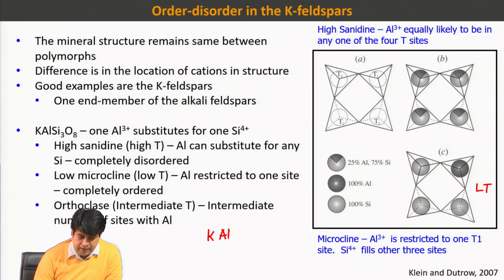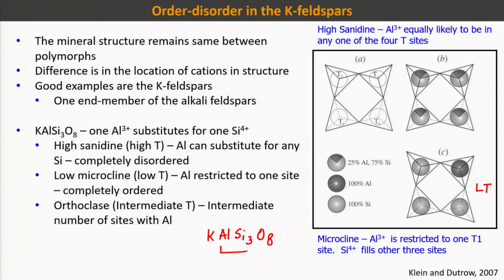So, if you see the formula of this K-feldspar, you have KAlSi3O8, and aluminum and silicon both are in 4-fold coordination. So, basically you have 3 silicon atoms and 1 aluminum atom. So, basically at a low temperature, because your structure will be perfectly ordered, your aluminum will go to the particular site and in all 3 other tetrahedral sites you will have silicon. Okay.